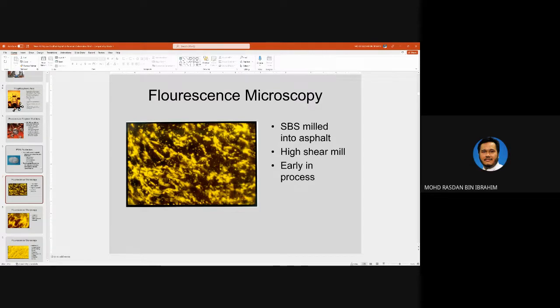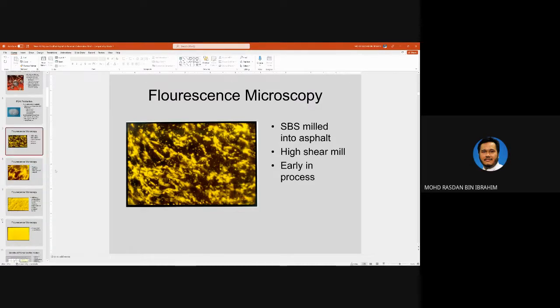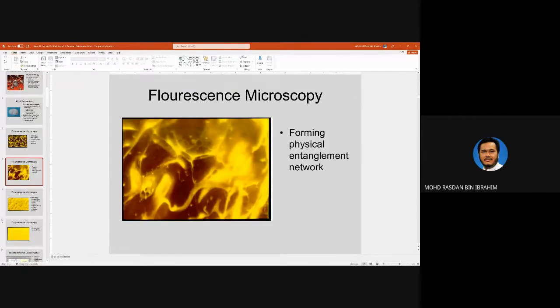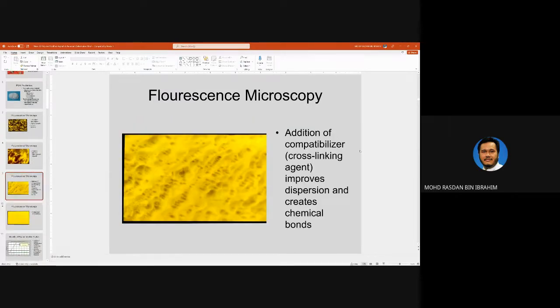So this is an example of a microscopic photo of bitumen mixed with SBS. This is early in the process, meaning that you heat up the bitumen and then you put the SBS in. After maybe 10 minutes, you take a sample and you can see the homogeneity of the mix is quite low. After some time, you can see that it started to even up. The particles there, and then it becomes better if you add compatibilizer or cross-linking agent.